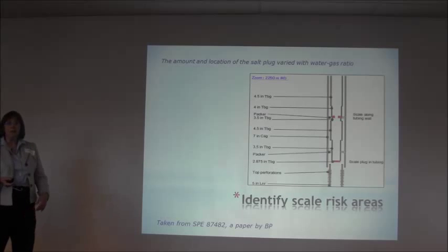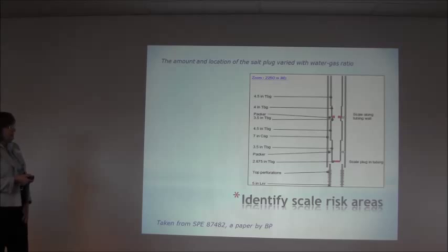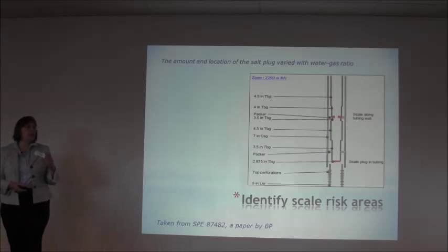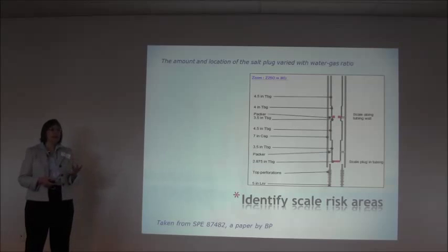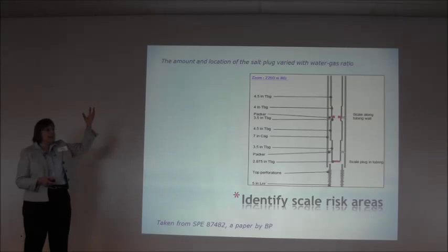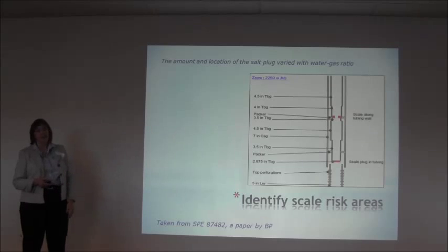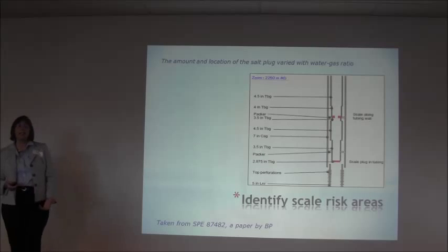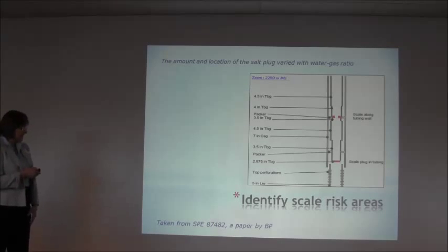What we were able to do from that was take the temperatures and pressures back, and we were able to understand that there were two places. There was a plug that formed entirely in the tubing at that particular spot, and then there was scaling along the tubing more, and then it also plugged up there. We could do that by understanding temperature, pressure, composition, deriving a reservoir brine, because we understood the formation, and taking that wellhead sample, coming down. So that's kind of how you get a scale tendency.